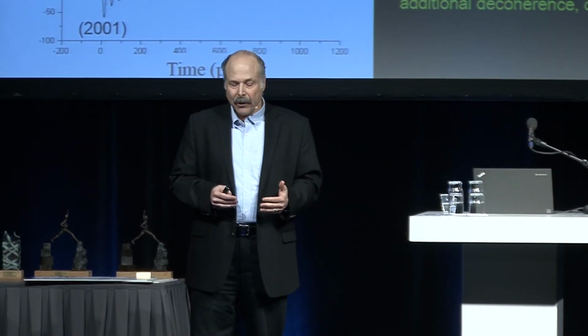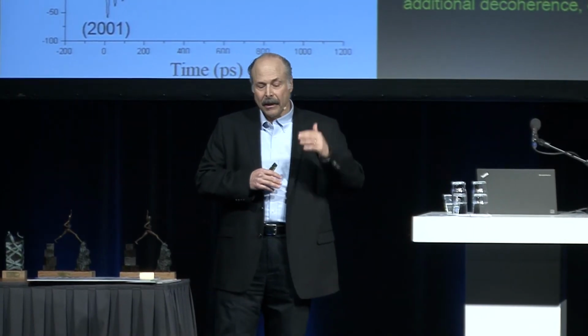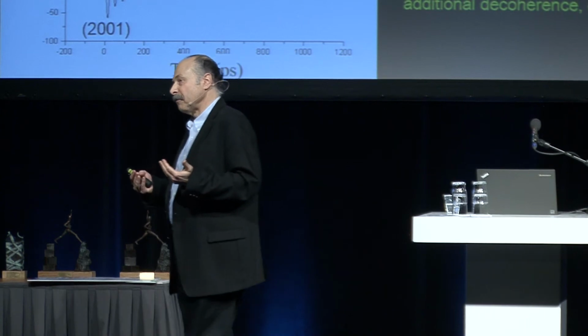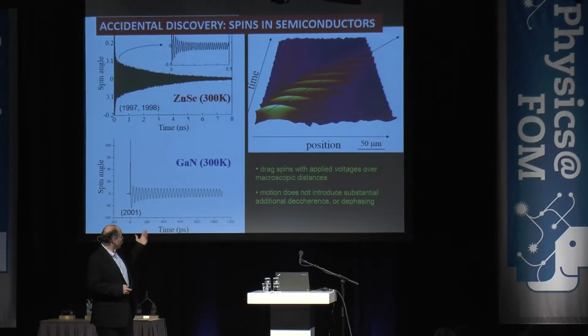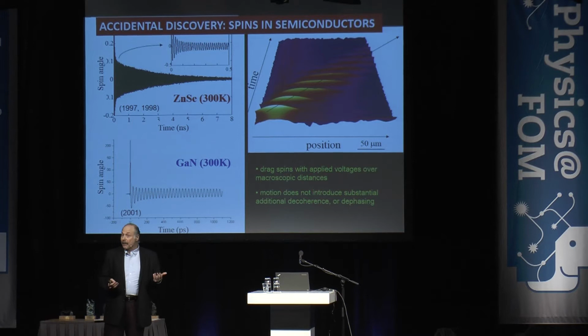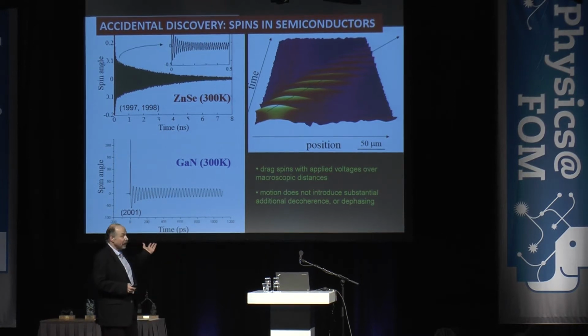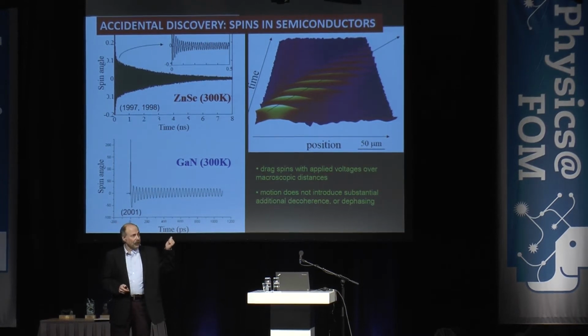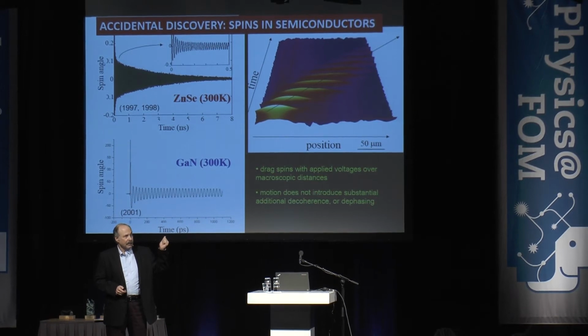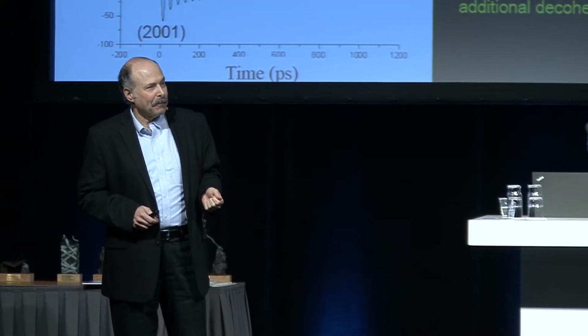That was at low temperatures, and then just by looking at different materials, by going to wider band gap systems, all this physics was moved to room temperature. And it was moved to room temperature in unusual but still commercially available materials, zinc selenide and gallium nitride. How many of you work with gallium nitride? This is a condensed matter meeting, right?